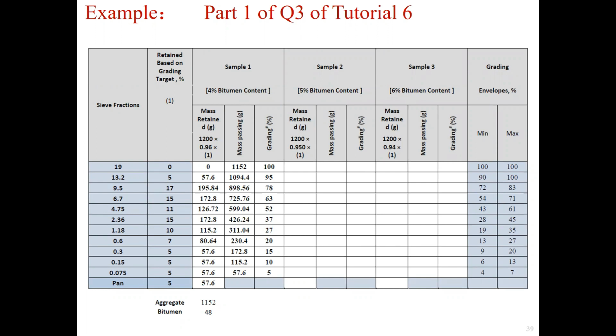1,200 grams. So for 4% bitumen content, the weight of bitumen is 48 grams, and the total weight of aggregate is 1,200 minus 48, equal to 1,152 grams. The upper and lower bound grading limit values are shown in the last 2 columns.